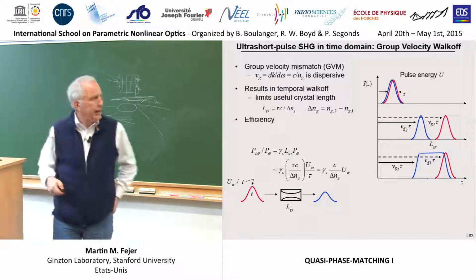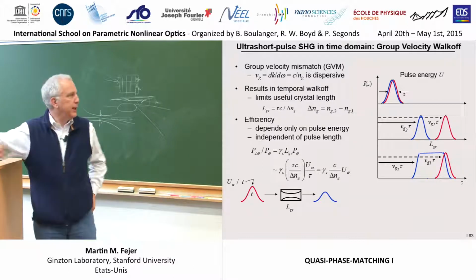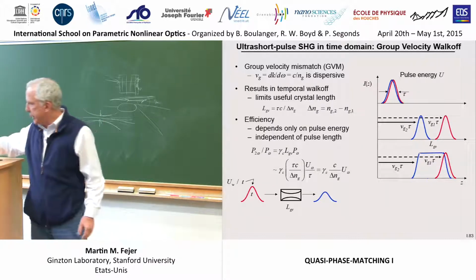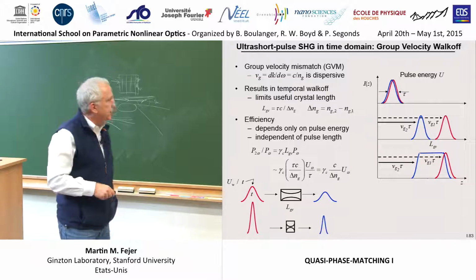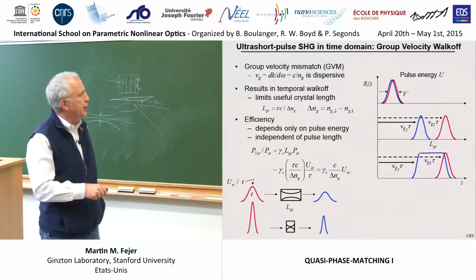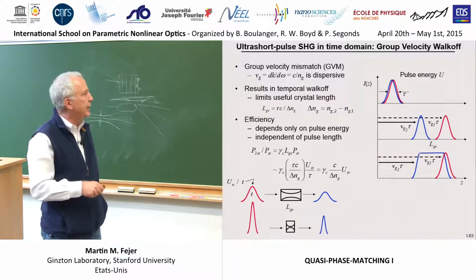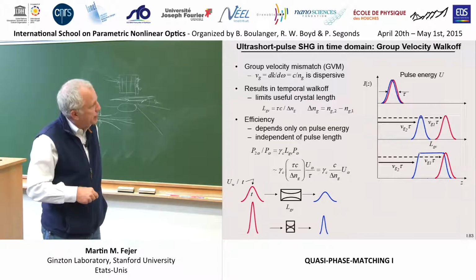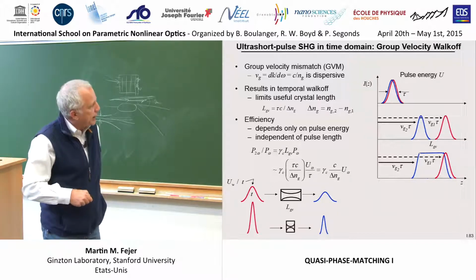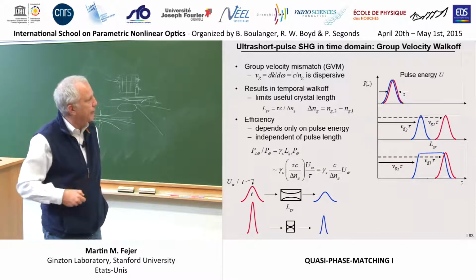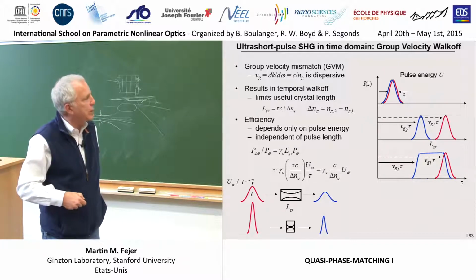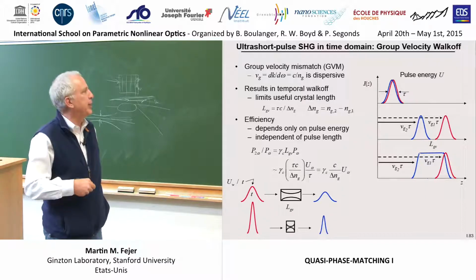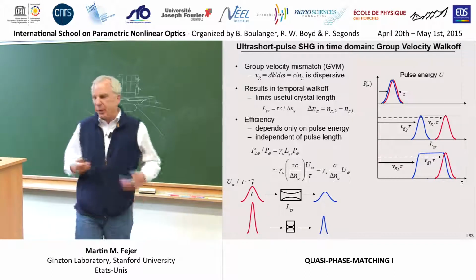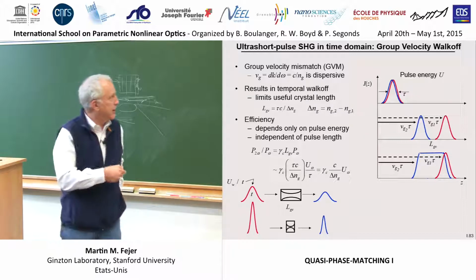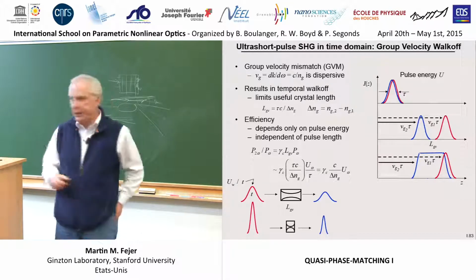And so what it means is if you go to a shorter pulse, you'll have a higher peak intensity, which will, in principle, increase your efficiency. But just as much as you've increased this peak intensity, the shorter duration requires a shorter crystal to avoid this walk-off effect. And so the amount of energy you generate turns out not to depend on pulse duration. If you choose this condition, it only depends on the pulse energy.